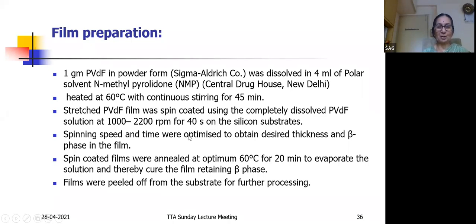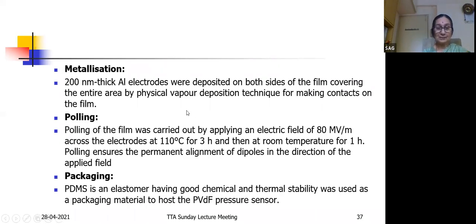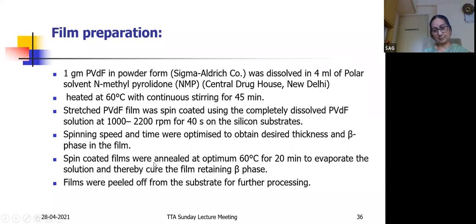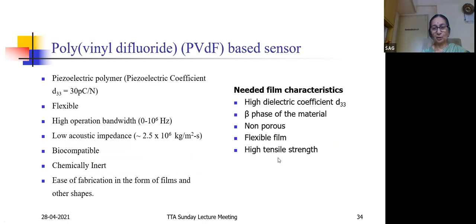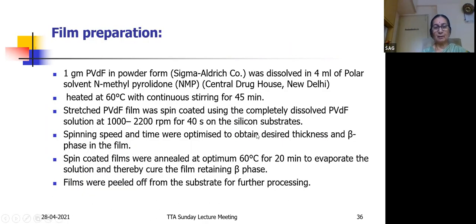Spinning speed and time were optimized to obtain the desired thickness of the film. The spin-coated films were annealed at an optimum 60 degrees centigrade for 20 minutes to cure the film and retain the beta phase. Films were peeled off from the substrate for further processing. We require a pore-free, non-porous material, and therefore we had to heat it, anneal it.